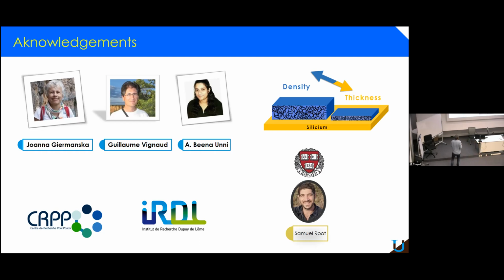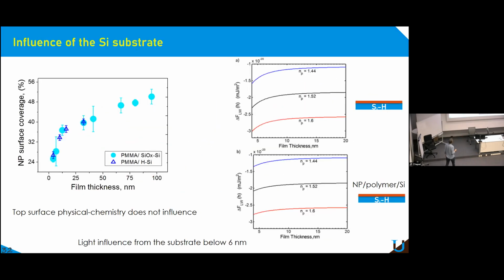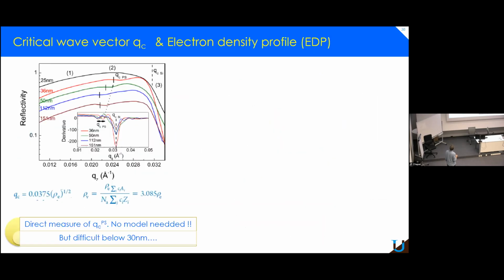The only thing that we did is with the reflectivity, when you see the typical curves of the polystyrene. So those are the reflectivity curves. Here you have the critical wave vector for polystyrene, and you can see it by eye. From theory, you can access the electronic density directly from the position, so you don't need any model. But you cannot do it when the thickness is very small, because you cannot see the critical edge anymore.